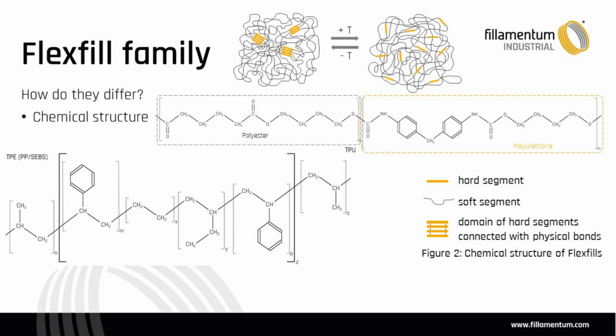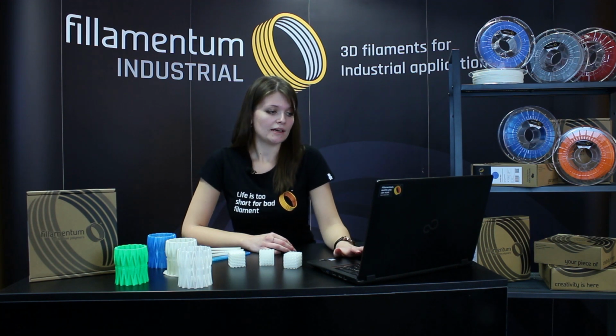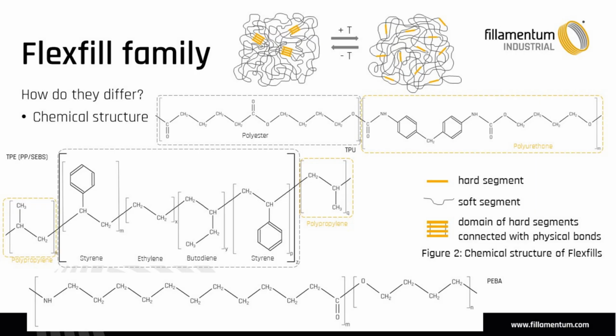Here is TPE. It is formed from polypropylene hard segments and SEBS soft segment. And PEBA is our last flexible polymer that is quite new. It is based on polyamide 12 hard segment and polyether soft segment. So we can see that it really differs a lot. Polyether, polyester, SEBS, they are totally different. Therefore, these flexible materials behave differently under mechanical stress. And the hard segments, polyurethane, polypropylene and polyamide, lead to different chemical resistance.